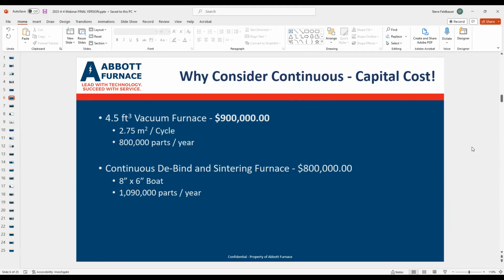Now, a continuous debind and sintering furnace that is designed for additive manufacturing would come in right around $800,000. So it's slightly lower capital cost. And this type of furnace uses an 8-inch by 6-inch boat. And it would have a capacity of just slightly over 1 million parts per year. So they're comparable in size.